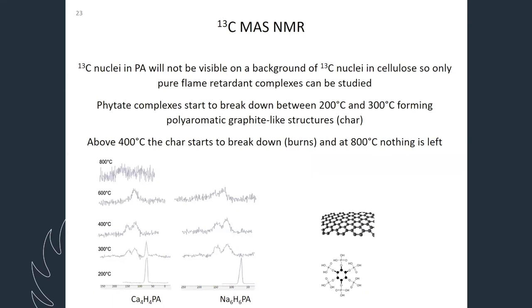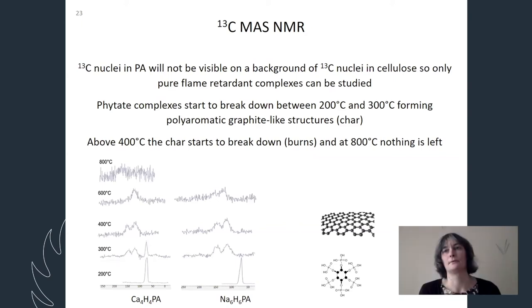Yes, we wanted to investigate our samples then. What has happened with these different temperatures, since we saw from the TGA results that they lose the mass and the pyrolysis starts at different temperatures. But what is happening with the flame retardant? What do we get instead? So when we took those samples from the furnace and then when they had cooled down, we did NMR measurements on them. NMR is nuclear magnetic resonance.